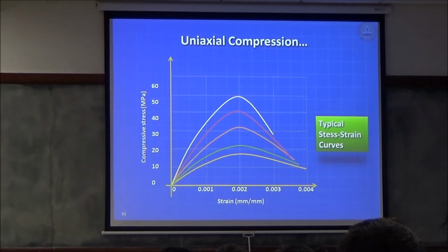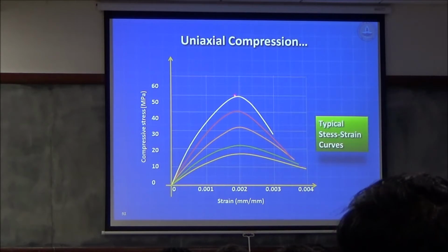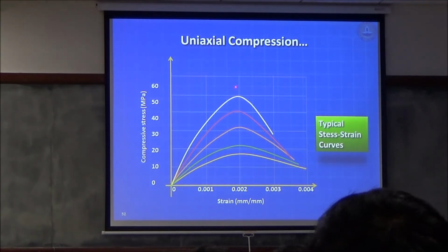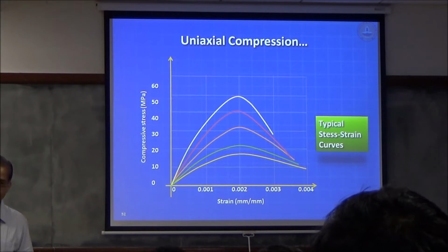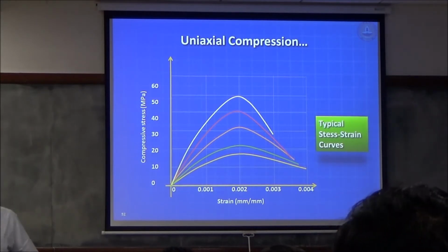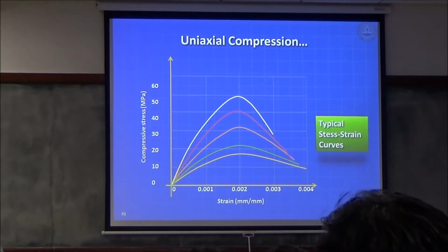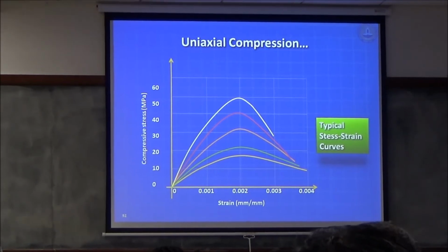Peak value remains same. All right, that's an interesting observation. Apparently, more or less, the strain at which the peak stress is hit is roughly the same. That's a good observation. They all hit the peak at roughly the same strain, and that's the reason why in our code they say in axial compression, take the strain as 0.002. Okay, good. First observation. Any other?